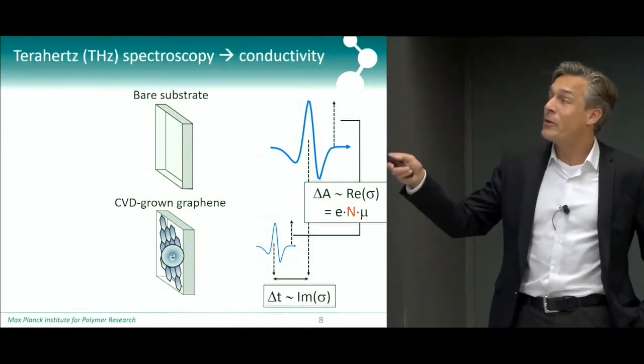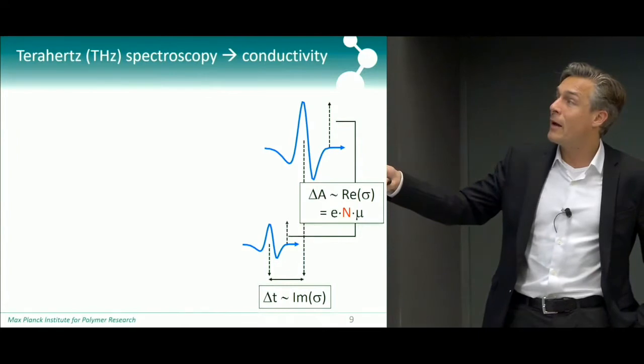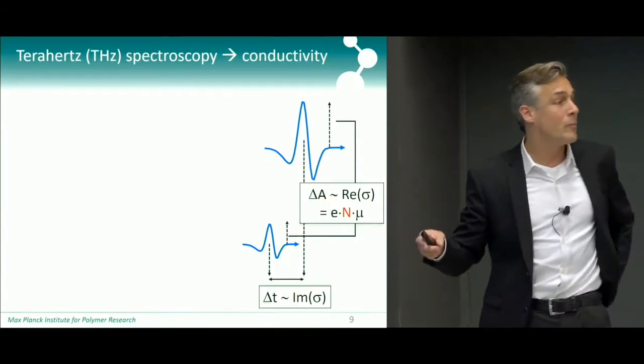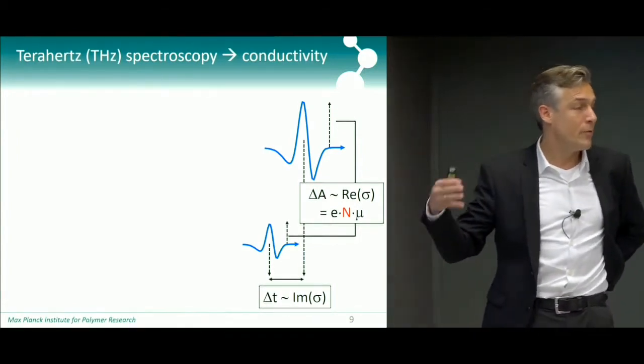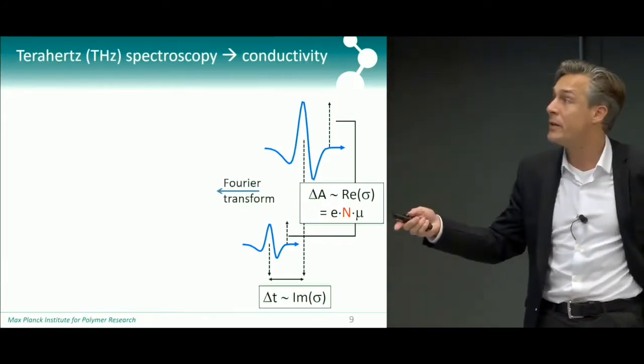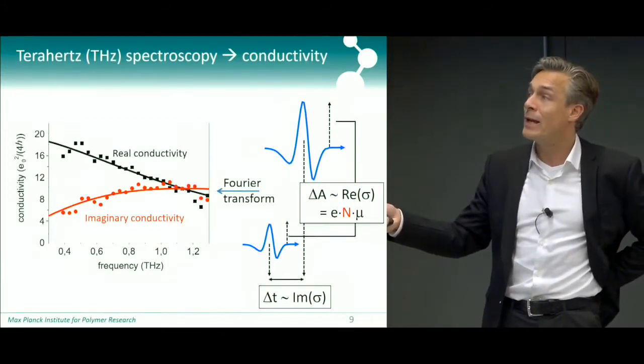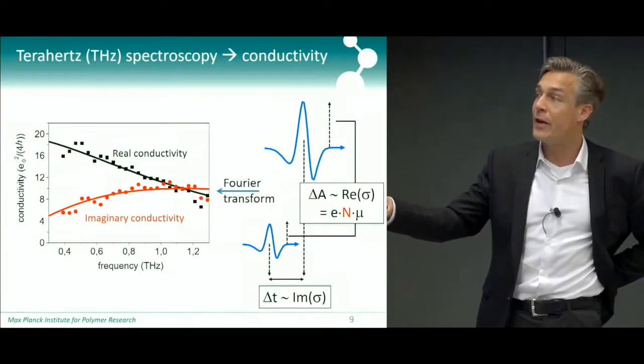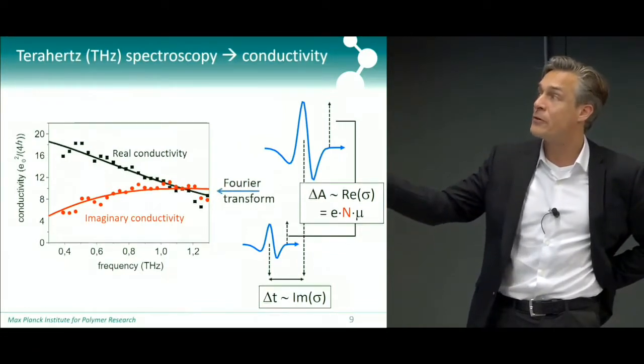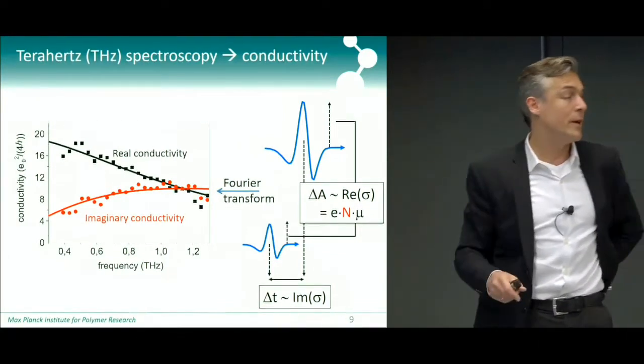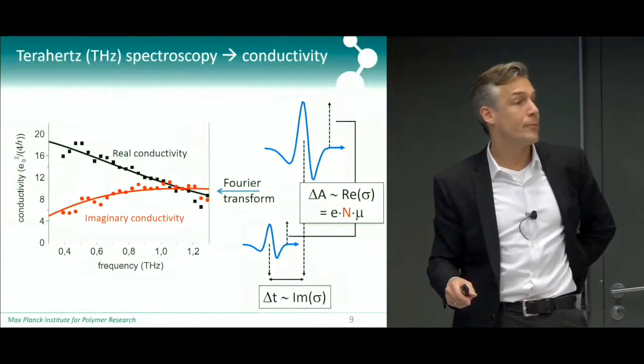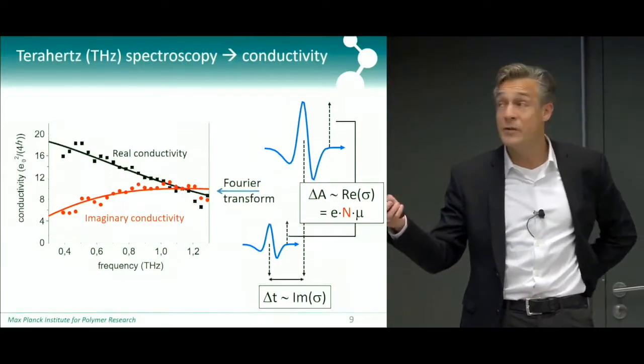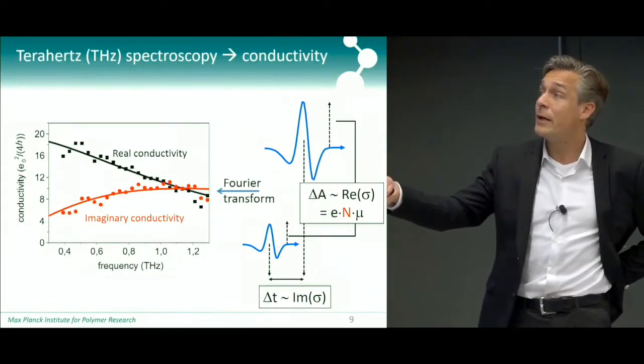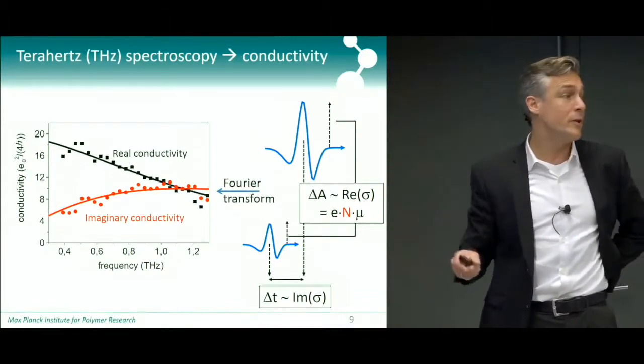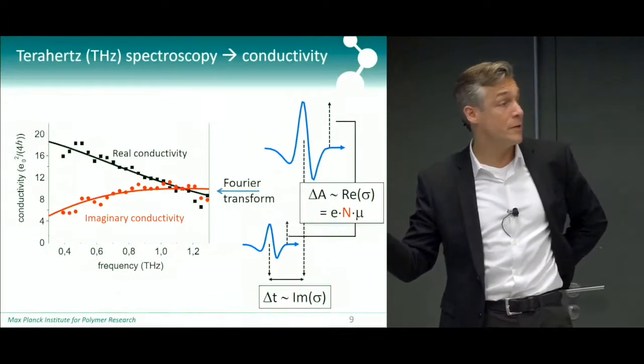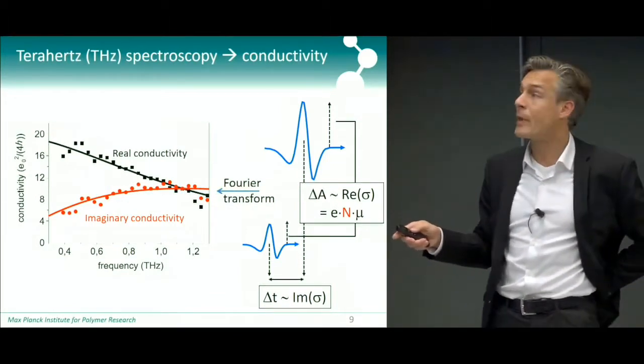Anyway, so what we do now is we analyze these, they're called waveforms, in the frequency domain. So we Fourier transform essentially the difference of those two, and that gives us the conductivity as a function of all the frequency components that are contained in that waveform. So this gives us the frequency-dependent real and imaginary conductivity of a monolayer of graphene. Okay?